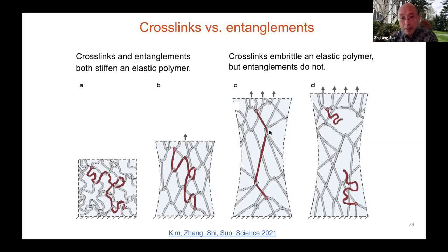Why? Because at an entanglement, the polymer chain can slip. So before the chain breaks, the entire tension is transmitted along the entire chain, across the entanglement. Entanglement does not break the transmission of high tension. When the chain breaks at a single atomic bond, the entire chain loses its energy, right? So now, this paper plays this game.